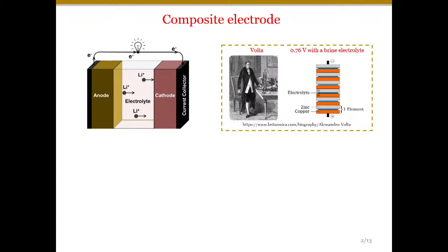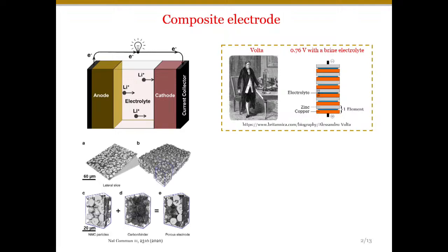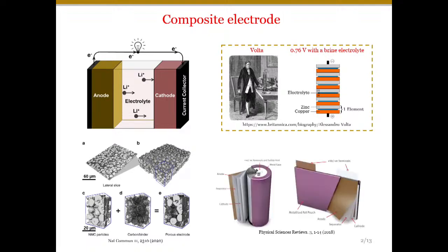Comparing with respect to what electrodes were made of during early demonstration around 1800, they used to be just metal plates. But if you compare them with more recent and commercial electrodes, they are more of a composite, where you have active material which stores lithium. There are carbon additives, binders, which essentially form a porous electrode. This form of porous electrode can either be coiled around to make a cylinder, or a prismatic or pouch cell form of configuration.